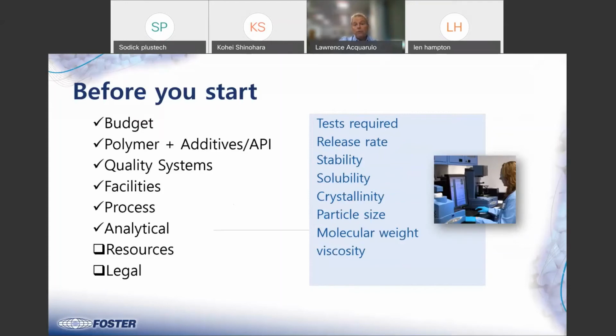And also, if we have to mill the polymer, we do a lot of milling of the polymer because it might be blended before it's compounded. So you want to get good blend uniformity. So we have GMP milling down to the micron size.